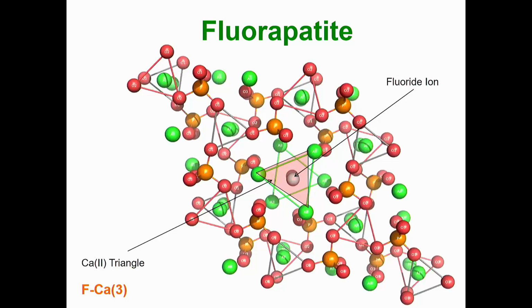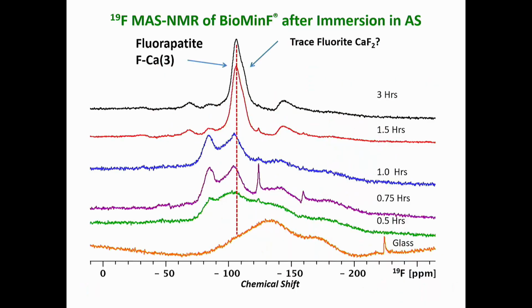This is the crystal structure of fluorapatite. At the centre of the crystal we have the fluoride ion that's marked there, and that is surrounded by 3 green spheres which are calcium ions. And we term this site in the fluorapatite lattice an FCA3 because it's a fluorine surrounded by 3 calciums. If we had a hydroxyl ion there, the hydroxyl ion would be displaced above the plane of the triangle, and that would result in the apatite being slightly less stable towards acids.